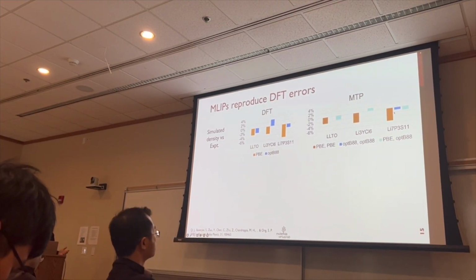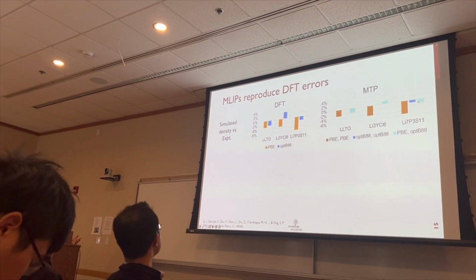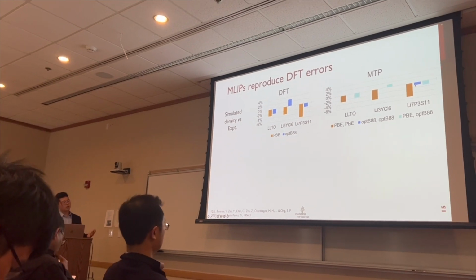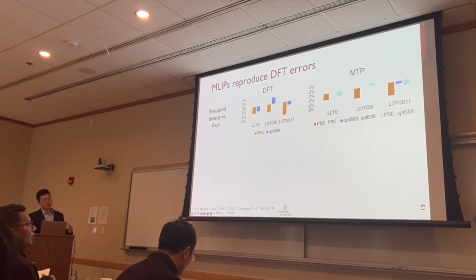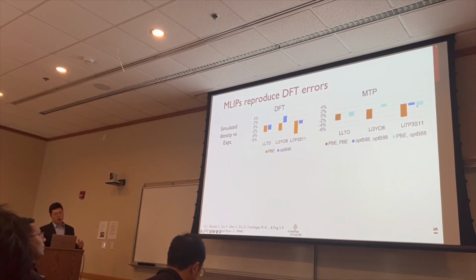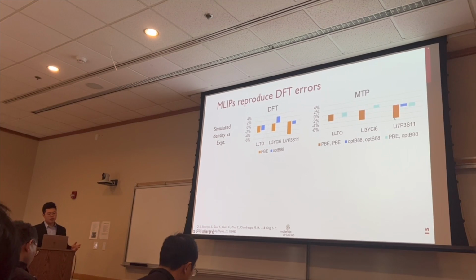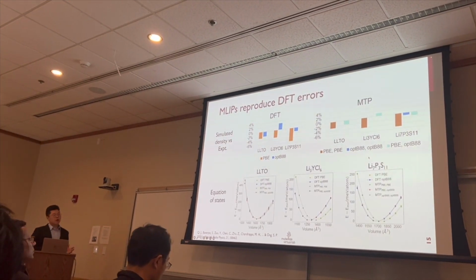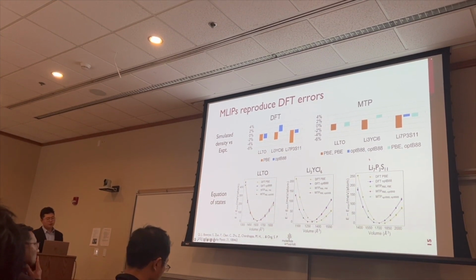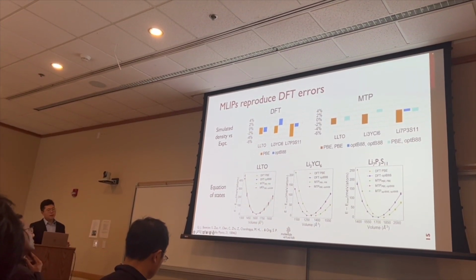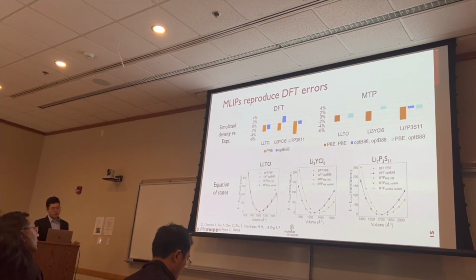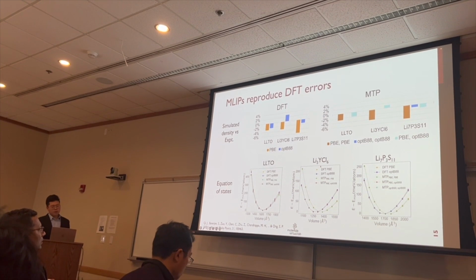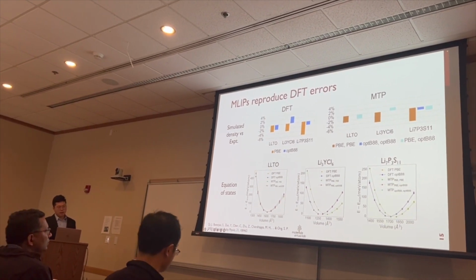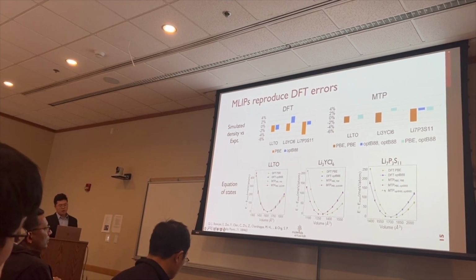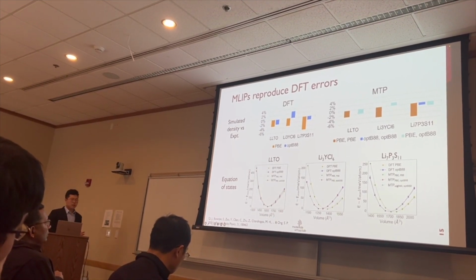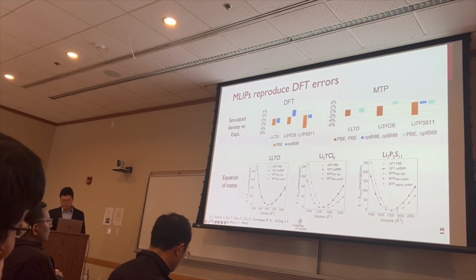This is reflected by the fact that no matter which functional is used in the generation of structures, the MTP always reproduces the result of the DFT functional after the comma, which is the one used to generate the training energy and forces. We observe a similar trend for equation of state simulation for all those 3 systems. For LTO, the PBE and OPTB88 got very similar results that are indistinguishable, while for LYC and LPS, we can see a clear, significant difference, and MTP again reproduces the DFT result with the functional that is used to generate energy and forces.